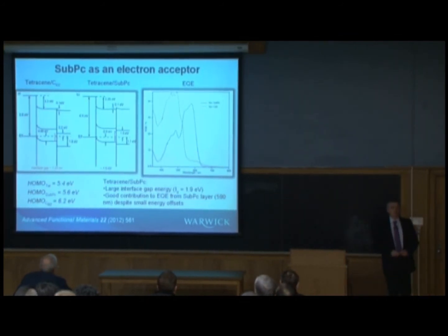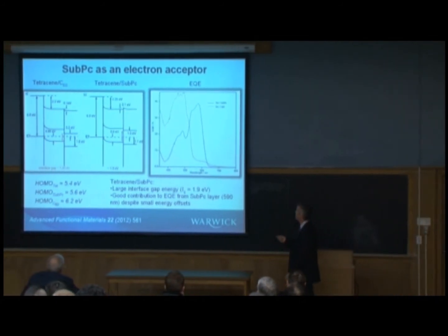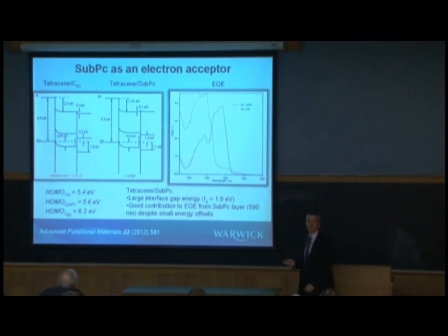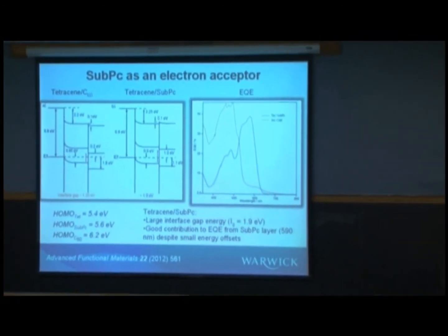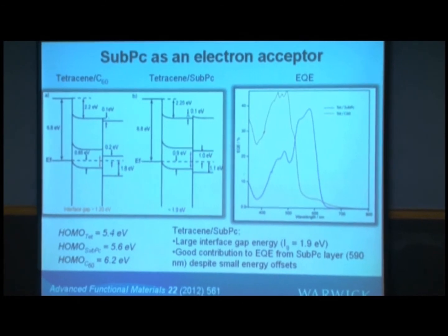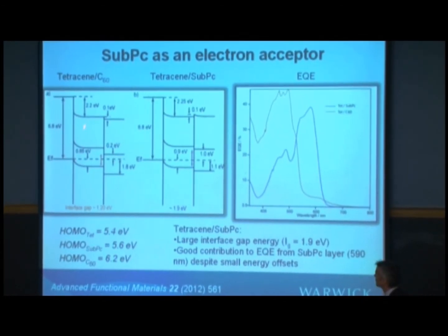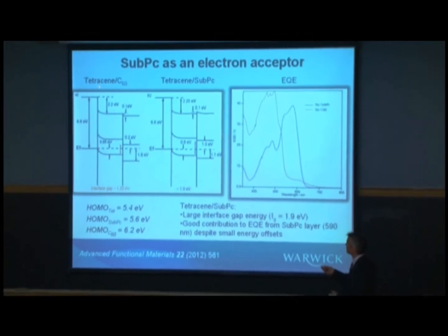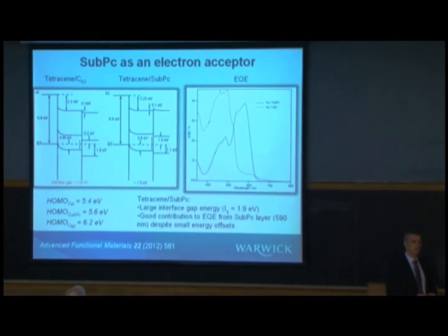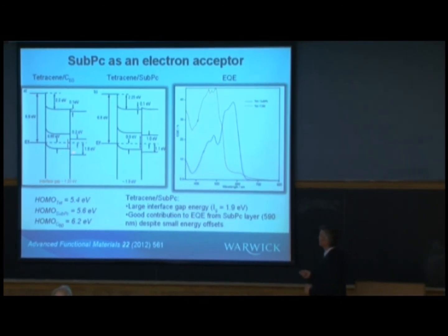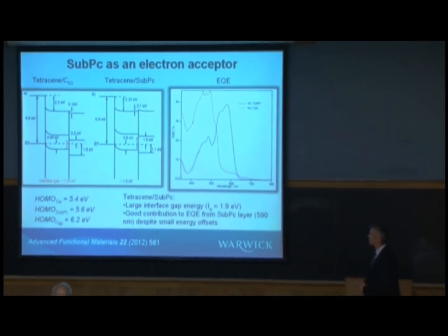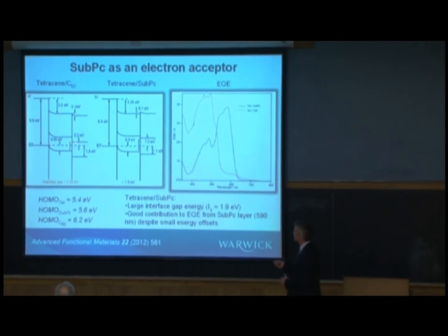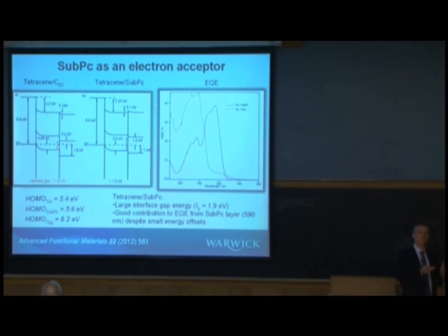So we explored the use of subphthalocyanine as an acceptor as opposed to a donor. So we replaced the C60 in our device. And the reason for doing that, if you look at the energetics here, this is 2 different materials. Tetracene now is the donor. C60 is the acceptor. And in this particular configuration, all this data again came from photoemission experiments. Then the interface gap energy is limited to about 1.2 electron volts. And that's simply because of the energetics of the C60 mean that you've always got such a large offset here, which gives rise to those big losses. So the voltage will be limited.